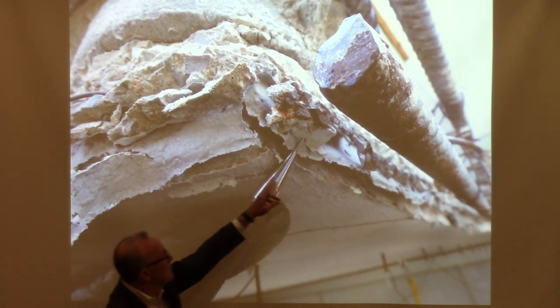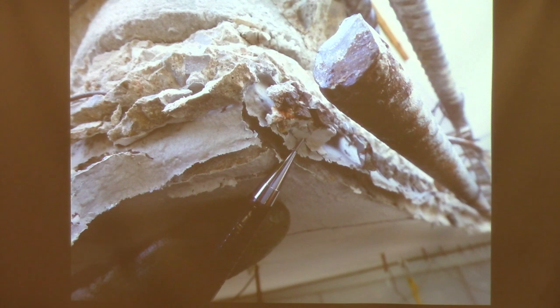Here's the concrete that's about ready to fall off, and then you see the bar with no cover with corrosion on the side. So knock all that off, put in the GFRP dowel bars and the GFRP detailing steel, form it up. In addition, it had to be designed for a rail load on the balconies to take a certain shear, and we're doing that by shear friction across that plane with the GFRP bar. You have to rely on the manufacturer; we required them to run tests on shear friction with the GFRP to make sure we had enough capacity.